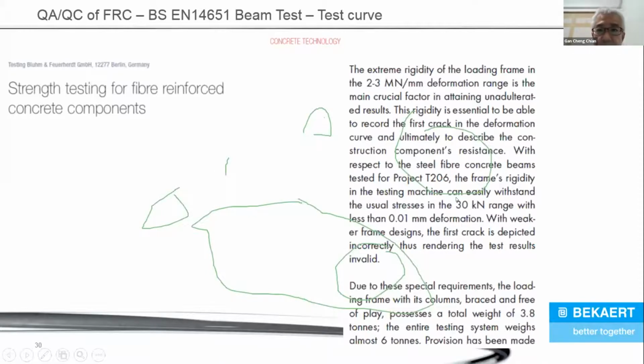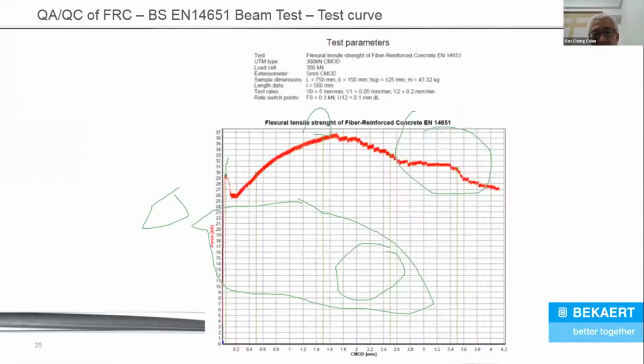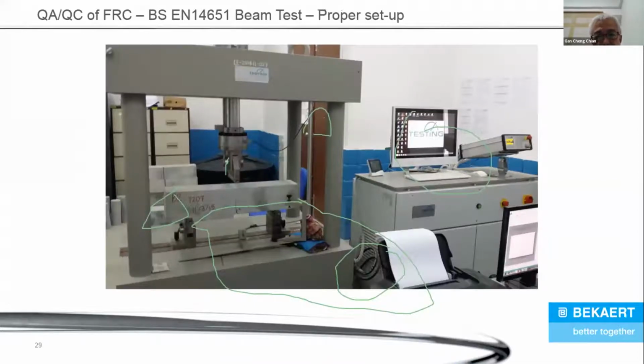So these are the requirements of the testing machine. Again, I took this from a magazine called Concrete Technology, and this paper appeared in this magazine, and it says like this: the rigidity of the loading frame in 2 to 3 meganewton per millimeter deformation range is the main crucial factor in attaining unadulterated results. So you must make sure that your test frame over here has a rigidity of 2 to 3 meganewton per millimeter.